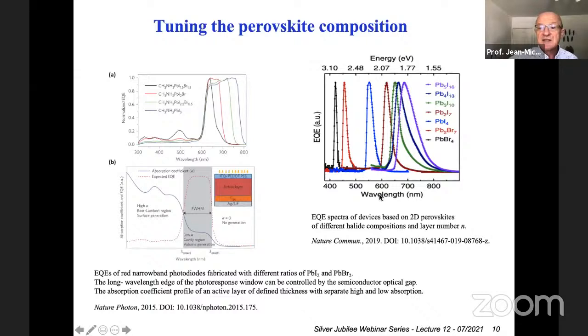Another design was by using different kinds of counter ions. By using different compositions, you can make different kinds of cation. You can make a two-dimensional perovskite, or you can deposit the two-dimensional perovskite by stacking single layers with different techniques. And it can also tune the band gap and the range of absorption. With two-dimensional perovskite, the range of absorption is more narrow, and this is a way in which it's possible to make photodetectors with multiple wavelengths of absorption.